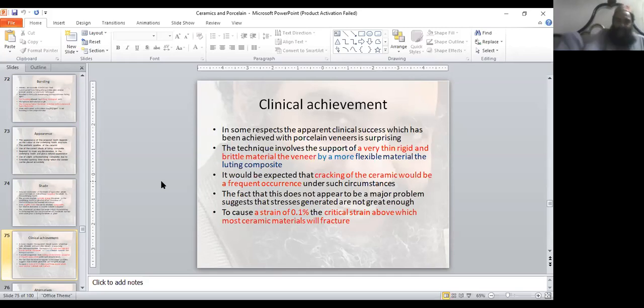And the clinical achievement, in some respects, the apparent clinical success which has been achieved with porcelain veneer is surprising. The technique involves the support of a very thin, rigid and brittle material, the veneer, by a more flexible material, the luting composite. It would be expected that cracking of the ceramic would be a frequent occurrence under such circumstances. Due to the mismatch, the fact that this does not appear to be a major problem suggests that stresses generated are not great enough to cause a strain of 0.1%, the critical strain above which most ceramic material will fracture.